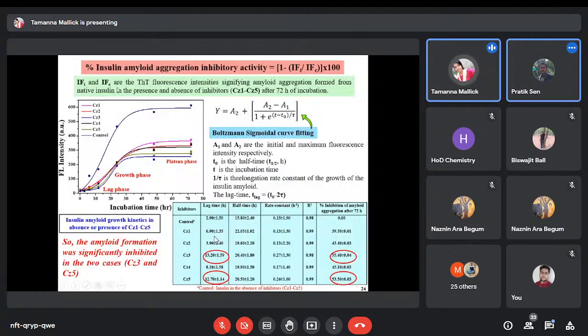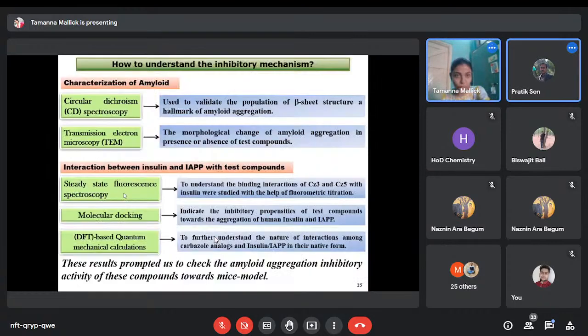Hence, by using the ThT fluorescence assay, we can calculate the percentage of insulin amyloid aggregation inhibitory activity by using this equation. And we found that the inhibitory activity of CZ3 and CZ5 is 55.4% and 53.5%. And also the insulin amyloid growth kinetics in absence of and presence of the carbazole analogs is shown here, and the extended lag phase of CZ3 and CZ5 indicates the slow nucleation process of the formation of amyloid.